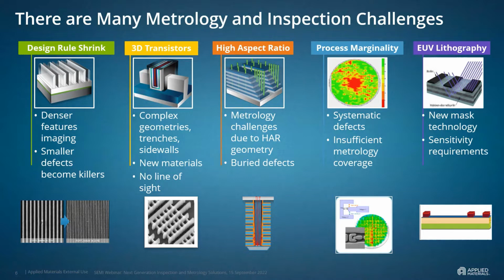In the center, we see high aspect ratio challenges, mostly due to 3D NAND memories, or VNANDs. Here the metrology challenge is due to the high aspect ratio geometry, and we also need to find buried defects in these extremely high aspect ratio structures. Because of the design rule shrink, the process becomes marginal, and we need to look for systematic defects, and we need to ensure sufficient metrology coverage to allow systematic and meaningful analysis. And finally, EUV lithography introduces new mask technologies and new mask challenges, as well as high sensitivity requirements due to the design rule shrinks.